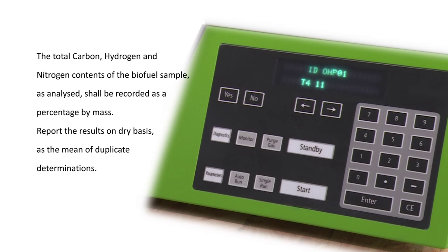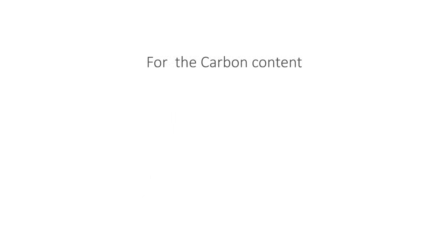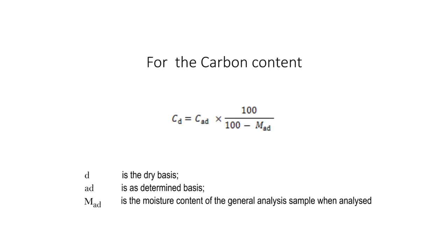The total carbon, hydrogen, and nitrogen contents of the biofuel sample, as analyzed, shall be recorded as a percentage by mass. Report the results on dry basis as the mean of duplicate determinations. The following equations shall be used for the calculations to dry basis.